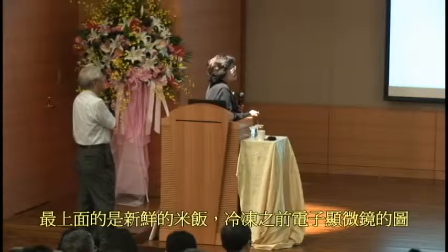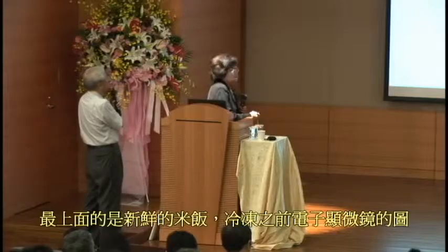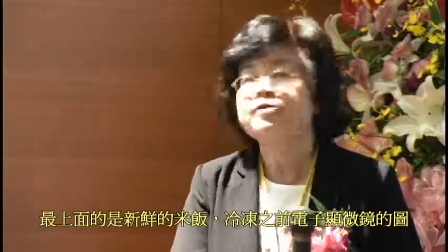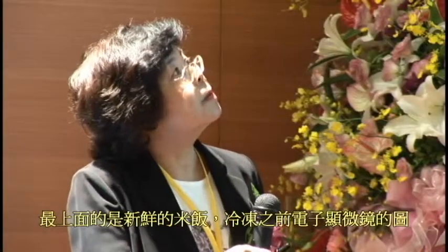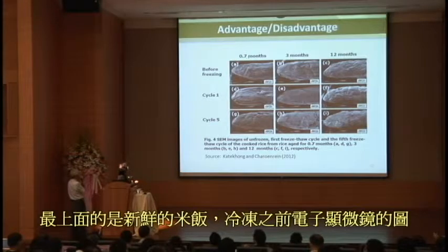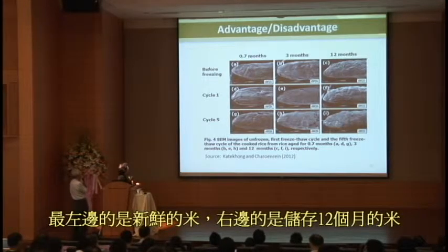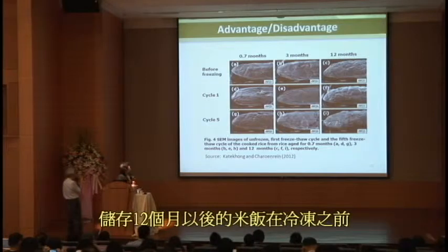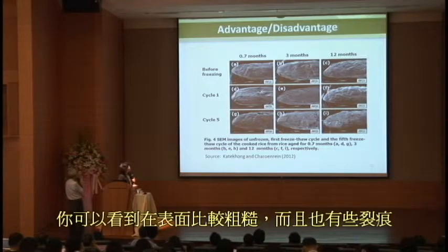This is the cooked rice, the same variety, which is RD 105, new, 0.7 month aging, and this one is 12 month aging. It's just cooked, and then we look at the microstructure with SEM. You can see that before freezing, the surface is a little bit different, more rough with the aged rice.